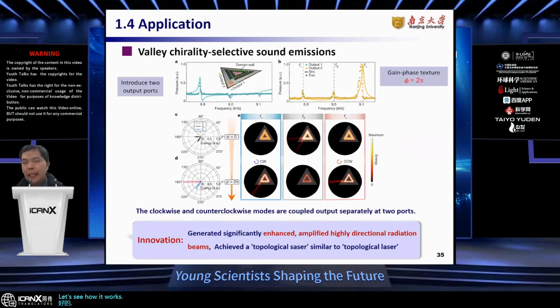All right, let's see how we can split and identify the different modes in our experiments. Let's talk about the gain phase of 2π. We measured the pressure amplitude at both output ports, and we can see that different clockwise and counterclockwise whispering gallery modes output through different ports. Now, for example, when the texture is 0, the breathing mode goes out in 2 directions from 2 ports. But when the gain texture is 2π, the clockwise and counterclockwise modes can be separated efficiently, and we can get really directional emissions that look like needles.